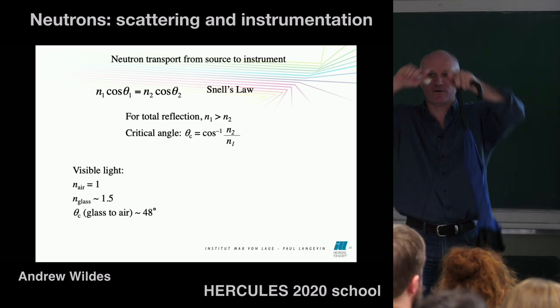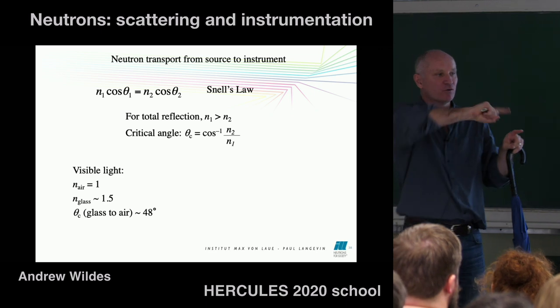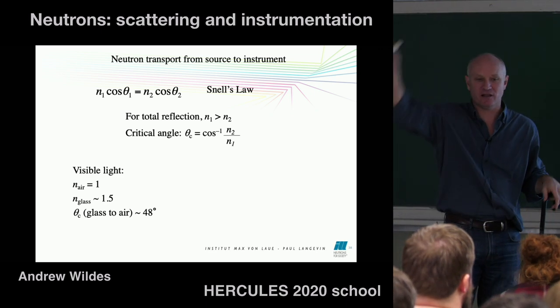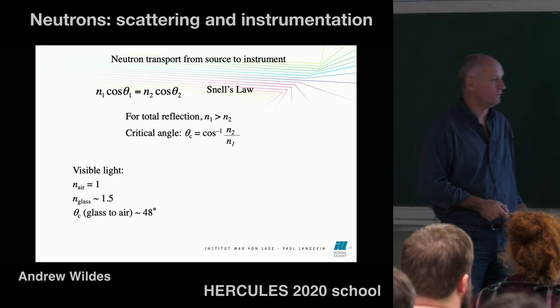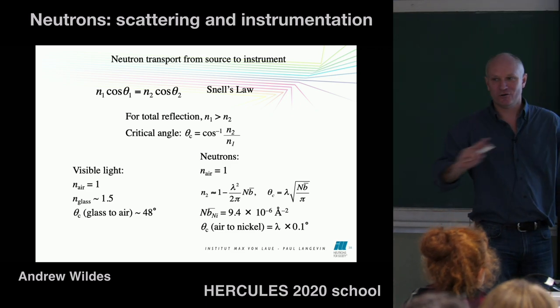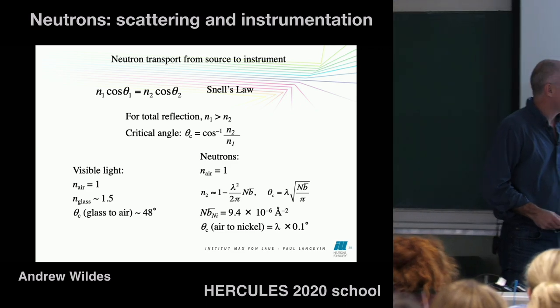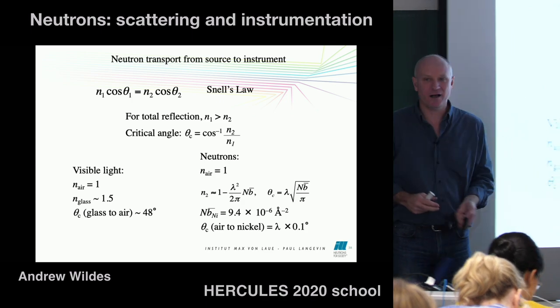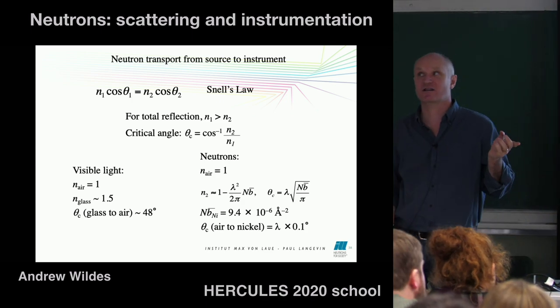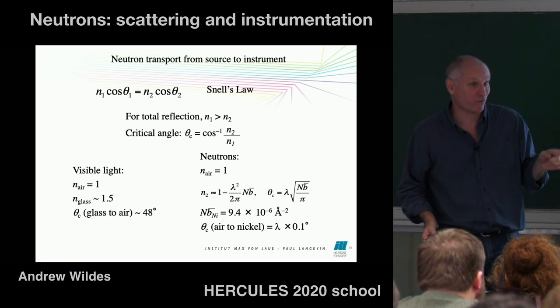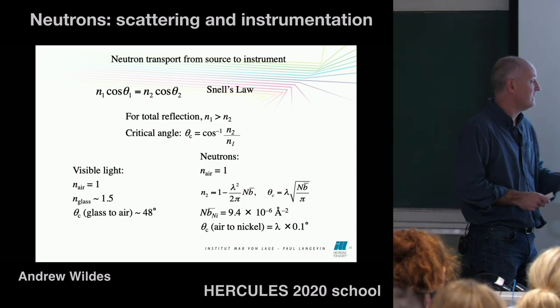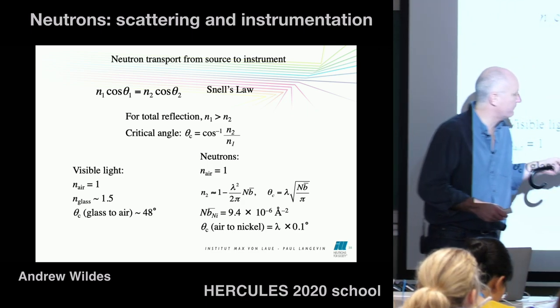So you can get an optic fiber and you can bend it quite a lot and you'll still get very good transport of the light inside the optic fiber. Very useful. For neutrons, though, not so much, all right? So the element with the smallest refractive index is nickel, right? This is the quantity here for the refractive index.